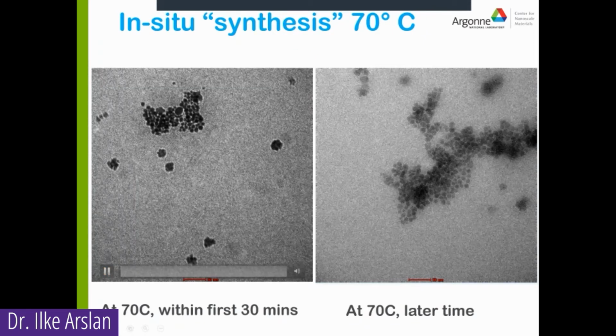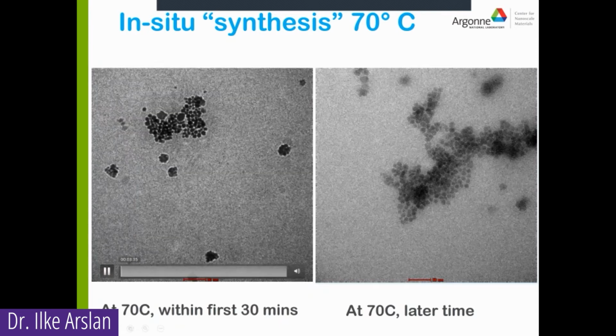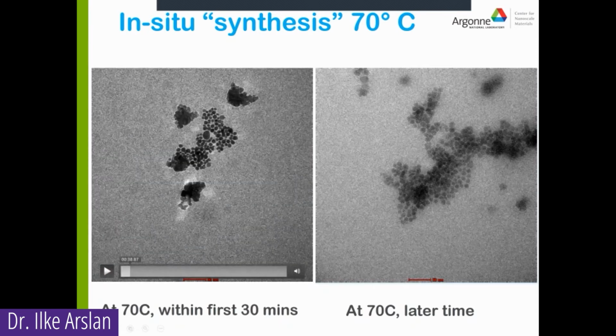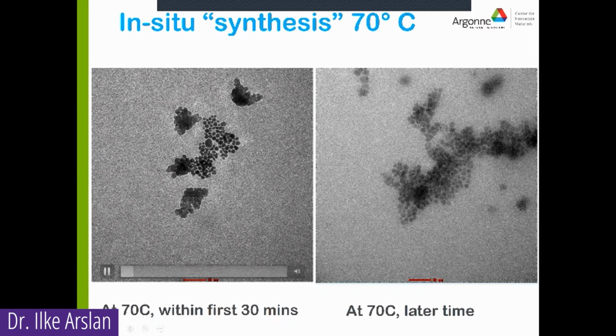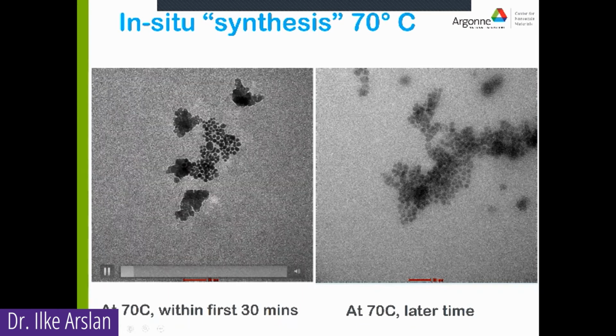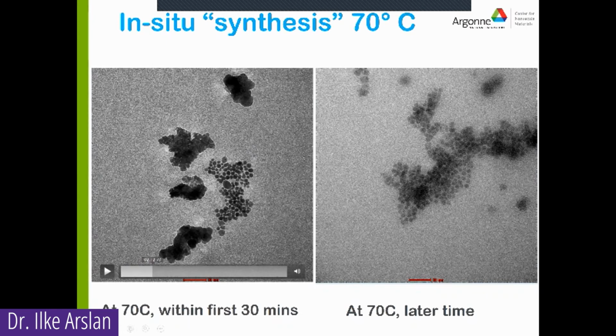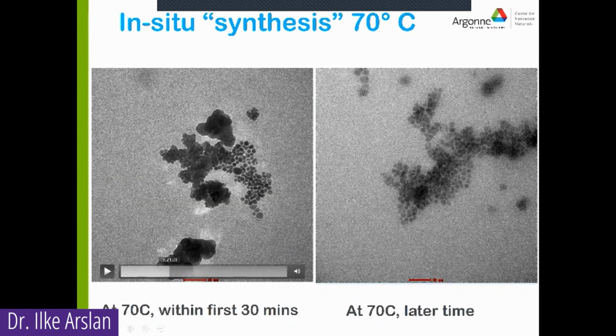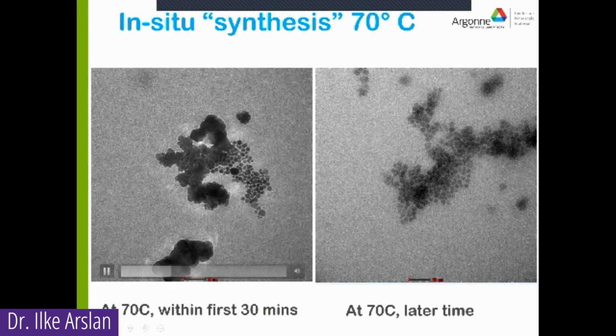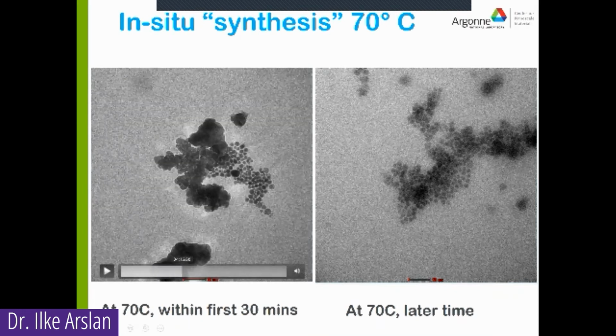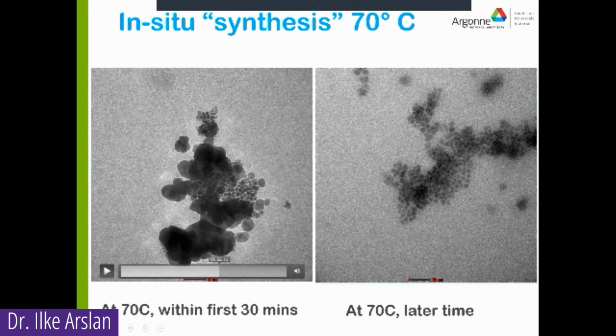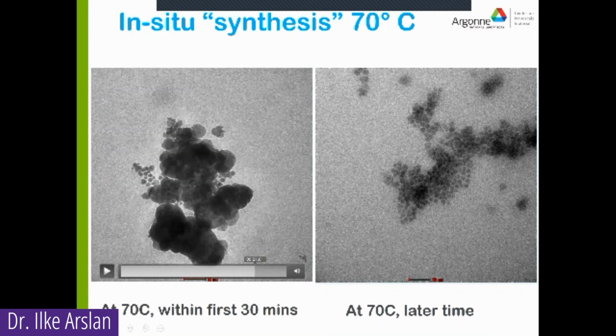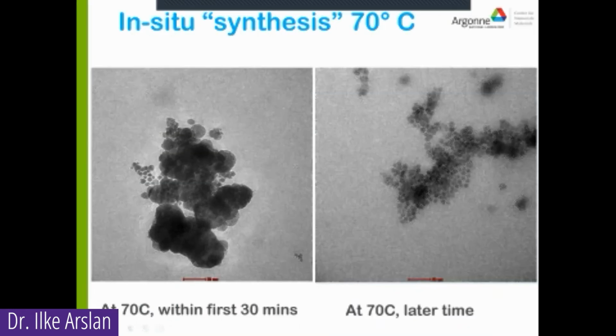And you can see that, I'm going to have to speed this one up too, that there are these particles that are still here, but there are these other particles that are growing from solution. So you'll see some popping up. So there's one growing right there out of solution, and more that are growing out of solution and coming together. So the story is not over.